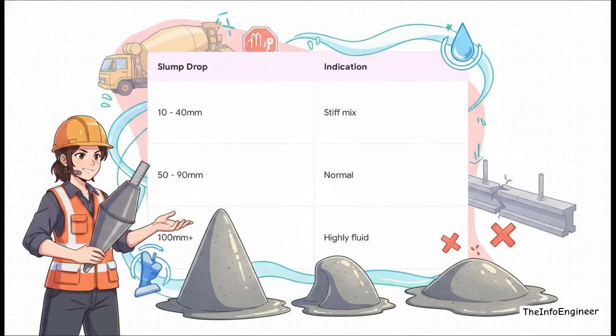Interpreting it is straightforward. A low slump drop means you've got a stiff mix, perfect for high-strength pavements. A medium drop is your standard for normal reinforced work. But here is the kicker. If you pull that cone and see a highly fluid slump of over 100 millimeters, but you know for a fact there are no superplasticizing chemical additives in that batch, your mix is fatally wet. The water-cement ratio is blown, the structural integrity is totally compromised, and you need to send that truck away immediately.